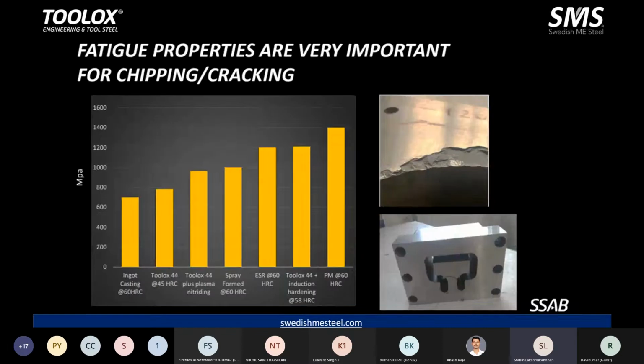As you will all understand and appreciate, fatigue properties are an important criterion for overcoming chipping and cracking problems in your molds. This graph gives you an idea of what Toolox and Toolox with different surface treatment processes can give you. As you can see, Toolox 44 plus induction hardening gives considerably higher values, even comparable to powder metallurgy steels. So that's the kind of options the material gives you.